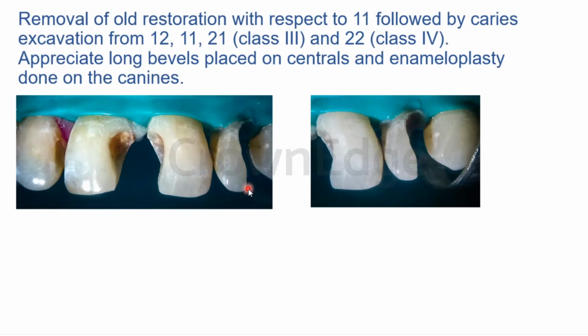Jaidev thinks that dehydration causes the dentinal tubules to occlude. Not really. It doesn't really occlude. Something collapses though. So can you find out what collapses when you air dry too hard? But good attempt. I would say that dehydration completely would cause a loss of bond strength, especially with the newer adhesive bonding agents that are there in the market right now. But there's something that collapses when you hit compressed air harshly over etched enamel or dentine. Tubules collapse. Yeah, that's pretty close.